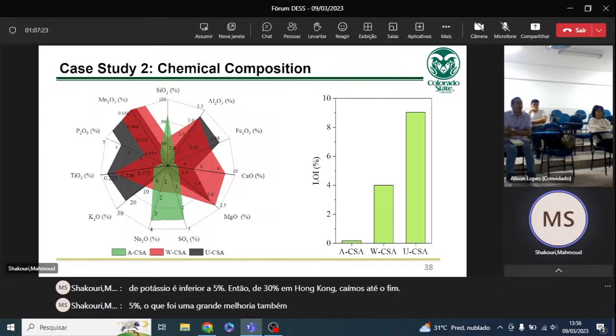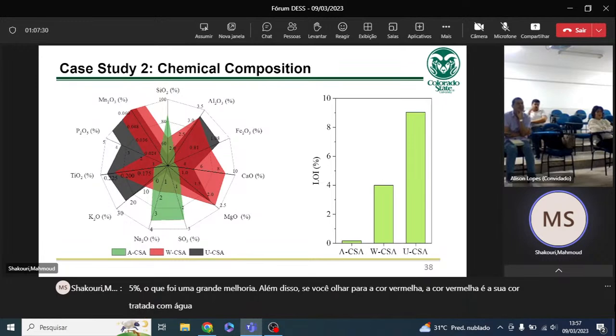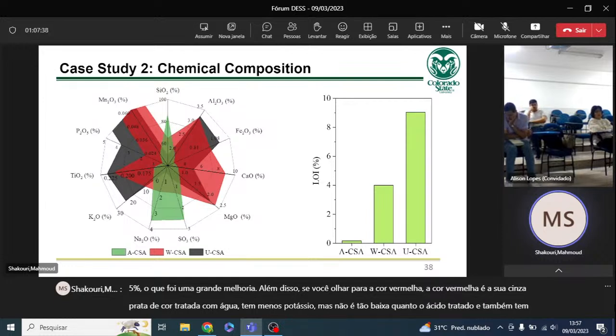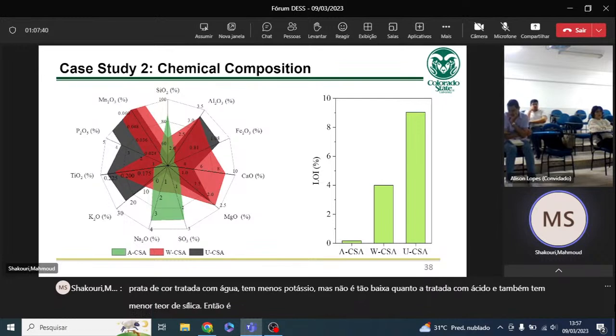Also, if you look at the red color, that is your water-treated corn stover ash. It has lower potassium, but is not as low as acid-treated. It also has lower silica content. So it's kind of something between untreated and acid-treated. So if cost is an issue, with water treatment you can basically do the same thing, but the quality is a little bit less good.